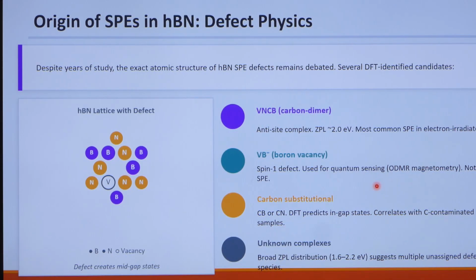So what is happening in that? Carbon is replacing that boron, and a vacancy is created at nitrogen. This is one kind of defect. That gives this anti-site complex, and this is the most common in single photon emission. The other is the boron vacancy, meaning a vacancy at the boron site. Above it was carbon at the boron site, and here it is a vacancy at the boron site.